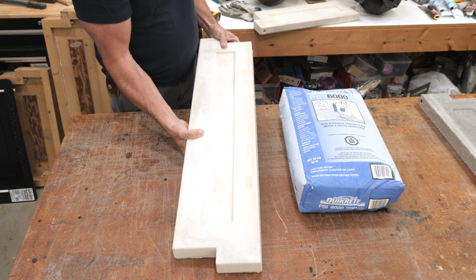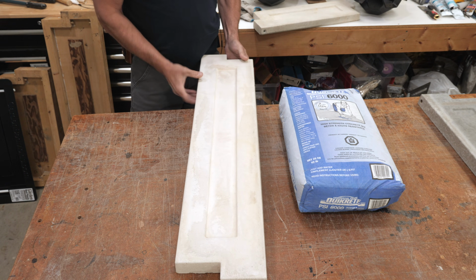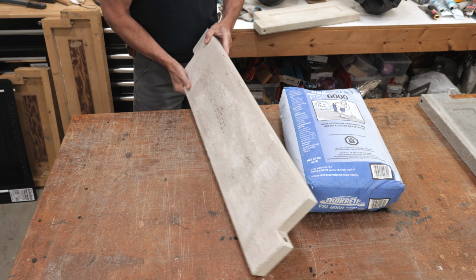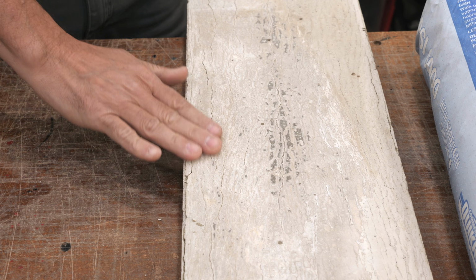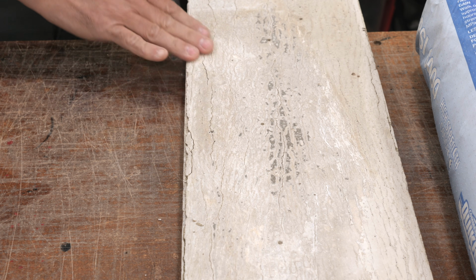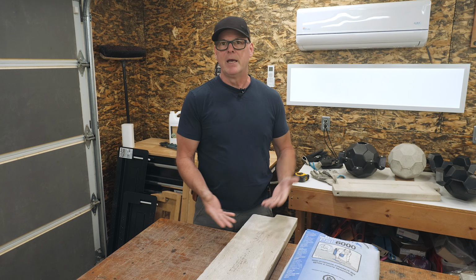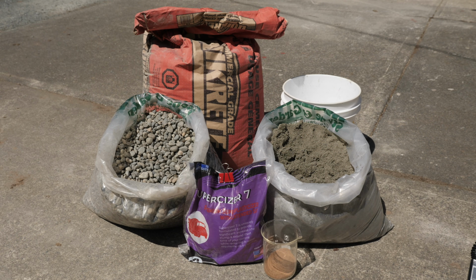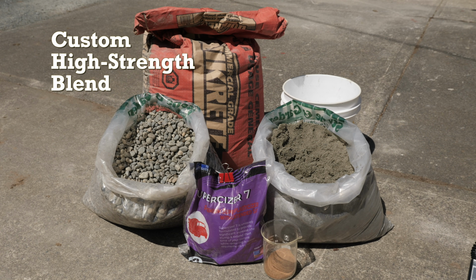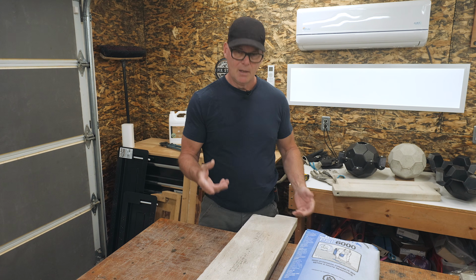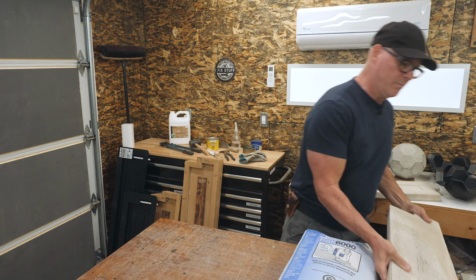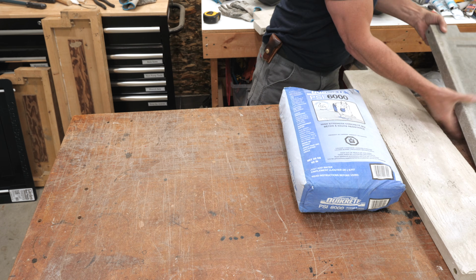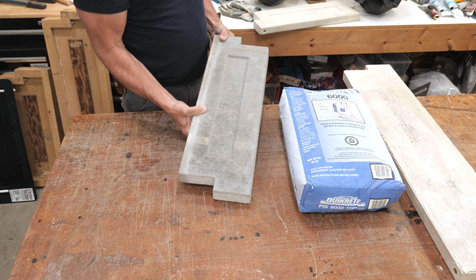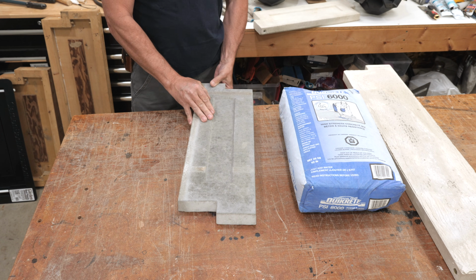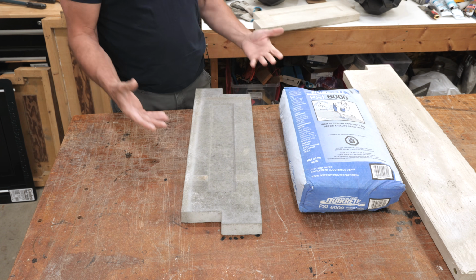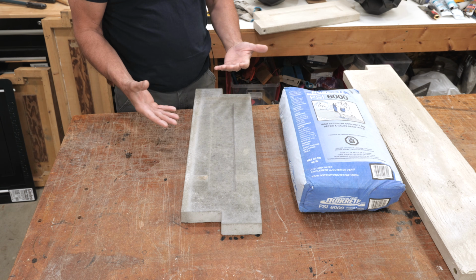In this CSA panel from the plastic molds, you can see these surface cracks. The panel is intact, but it's just not the best result. And all of that led to me formulating a Portland cement-based blend designed more for pouring countertops. Let me grab one of those. This panel was cast from that custom Portland-based blend in a plastic mold, and it looks great, and I was very happy with the results.